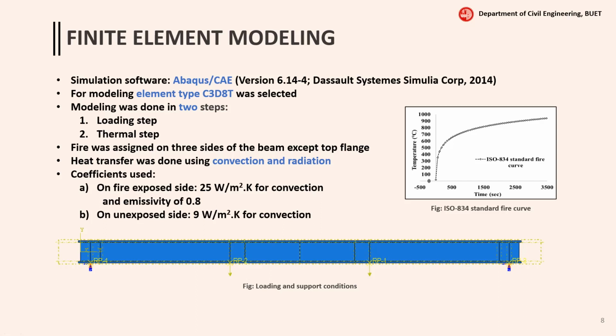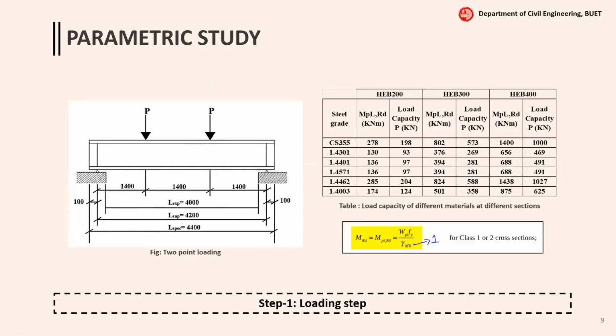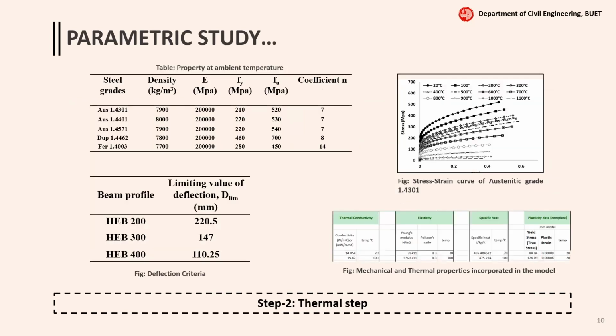As for the supporting conditions of the structure, at the left support, the translation in 3 directions was restrained, and at the right support, translation in 2 directions was restrained. All the rotational degrees of freedom were unrestrained. Moving on to parametric studies. For loading, we used 2-point loading at the desired magnitude, and the load was calculated using class 1 section of Eurocode. Since the characteristic properties of the different grades vary with temperature, we had to calculate the different mechanical and thermal properties of the materials and incorporate them in the model accordingly.